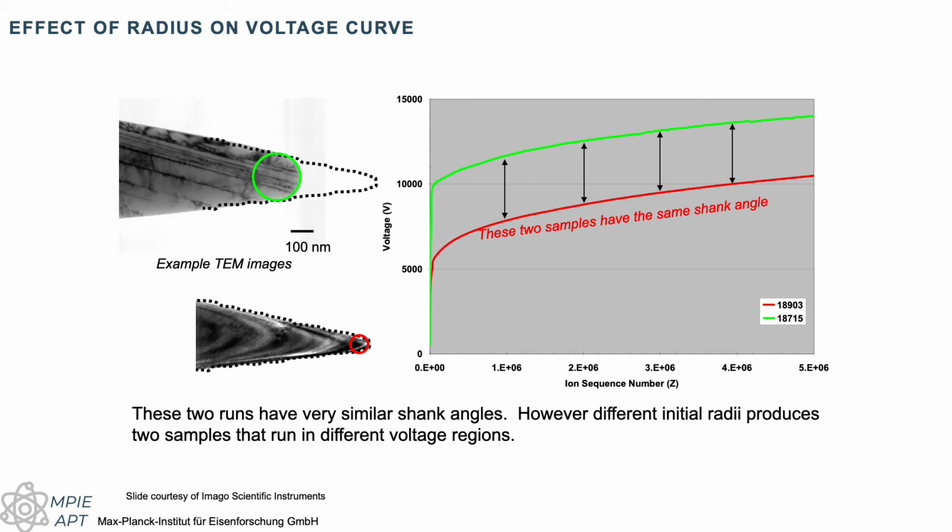But we still have some indications that they're not all completely bogus. So when we use the voltage, for example, if we took 2 specimens with more or less the same shank angle, we can see that the evolution of the voltage follows more or less the same trend, the same slope. So this seems to work okay.